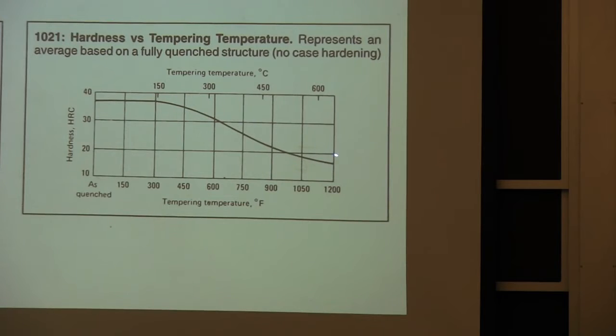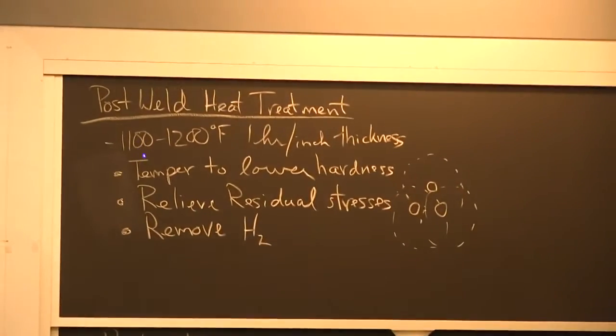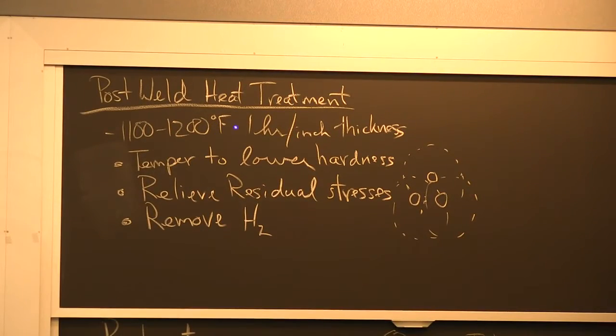But eventually, we're going to see that we do post-weld heat treatment up here in the 1100 to 1200 degree range. And in fact, I might as well do it here on the board. Post-weld heat treatment is another process that we might do for difficult to weld steels, where we heat them in the 1100 to 1200 degree Fahrenheit range, typically for 1 hour per inch of thickness. And that 1 hour per inch of thickness is, you can measure the temperature on the surface. You put it in some furnace, and when the surface gets up to 1100 degrees, you then need to soak it so the temperature on the inside gets there.